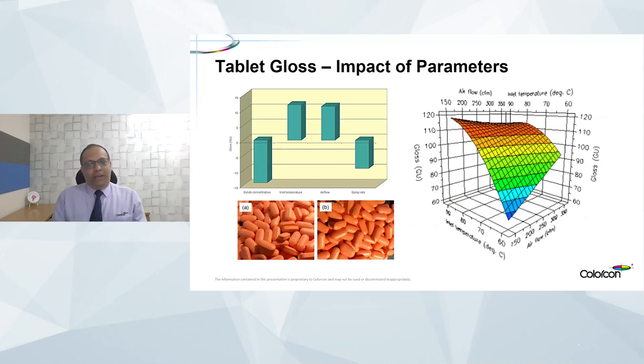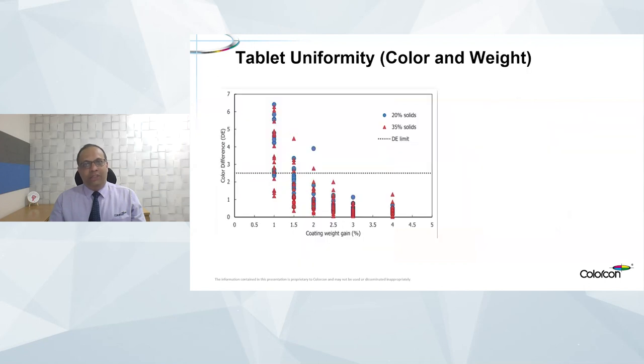Now, there was a question on the gloss, and maybe most of you have answered that correctly as well. What are the parameters that impact gloss? Again, looking at the thermodynamics and distribution, smoothness and gloss are related, in that better smoothness also has a tendency to have a good gloss. Of course, there are specially designed gloss coatings, examples like Opadry Gloss II, again, 85 series PVA-based coatings, that give higher gloss than the standard coatings that we sometimes use. But beyond that, maintaining a good temperature and airflow, and ensuring that the spray rates are controlled, gives a higher gloss. If you look at the surface response curve on the right, at the higher airflow conditions, as well as a good temperature, is where you get the maximum gloss, which is the orange and the red side of the surface response.